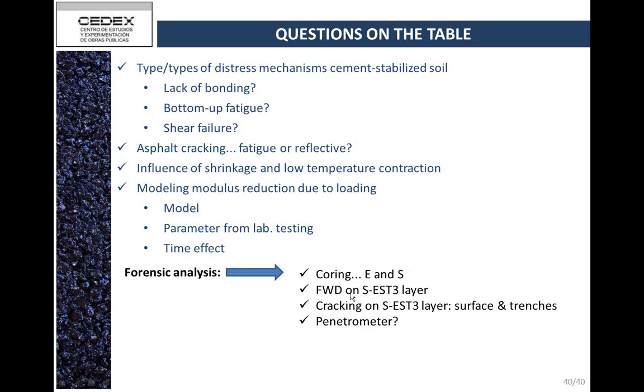We're also planning on doing FWD back calculation, but by applying the deflectometer load on the top of the cement-stabilized layer. We want to remove the asphalt layer, then put the falling weight deflectometer on the cement-stabilized layer, and then apply the load. This way, we will get rid of one of the unknowns in the back calculation, which is the asphalt layer. So we are expecting to have reliable results by conducting this test.